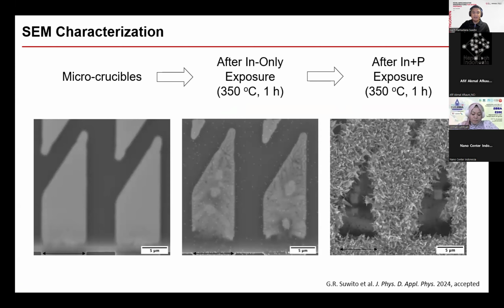And this is the SEM image after the 1 hour indium only exposure. We can see that a lot of indium particles are found across the sample as bright dots in here. In addition, you can also observe that the gold agglomerates into islands. There are main islands, which are still gold-silicon eutectic, possibly gold-silicon-indium eutectic. Interestingly as well, some main gold islands are located very near the opening, but some are very far away from the opening. And finally, after simultaneous indium and phosphine exposure, we can see that unintentional indium phosphide nanowires are formed everywhere on the capping layers. But fortunately, we can still find some regions on the microcrucible where we can still see the main gold islands under SEM. You can see this clean area.